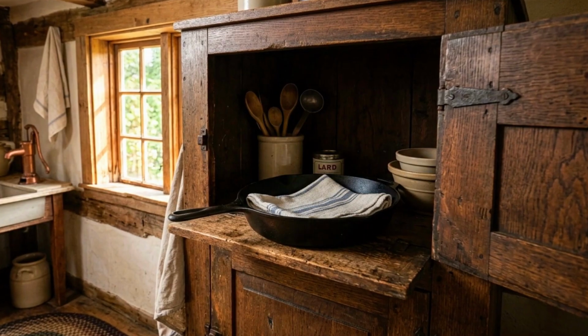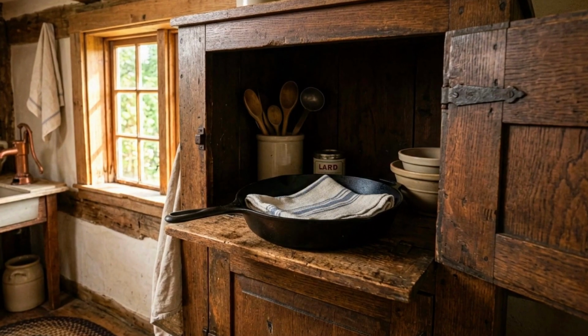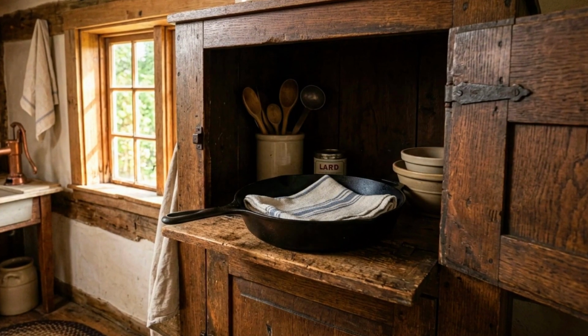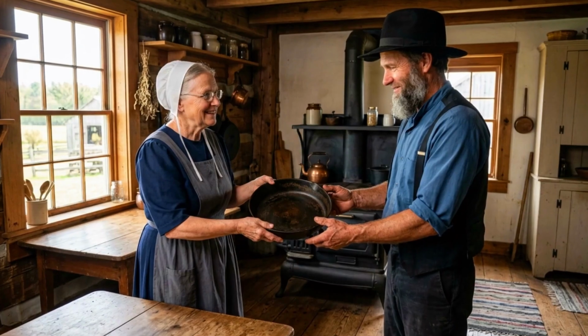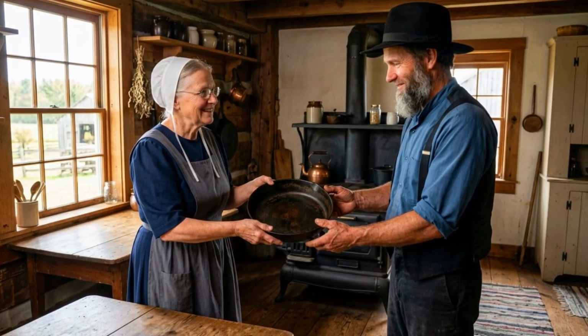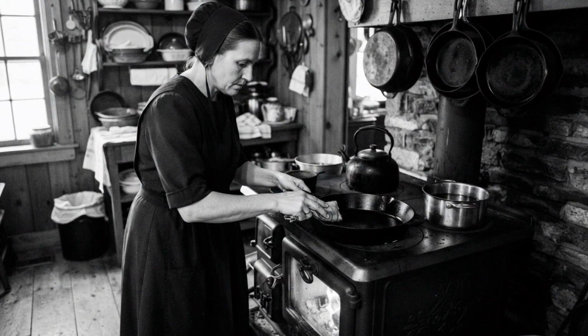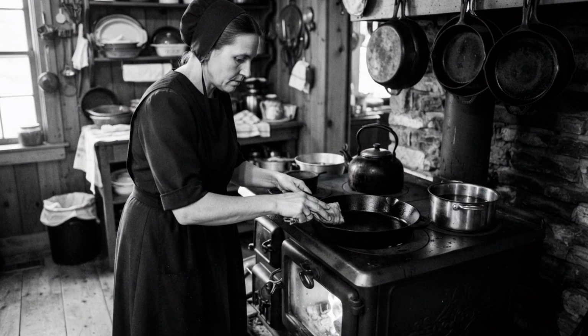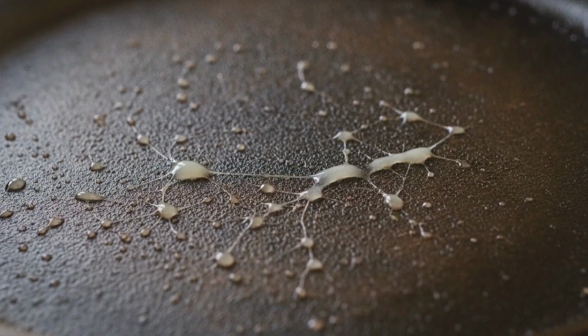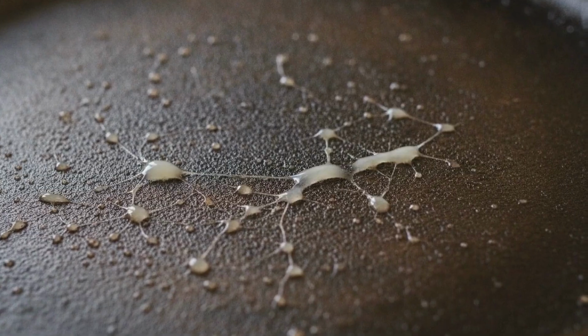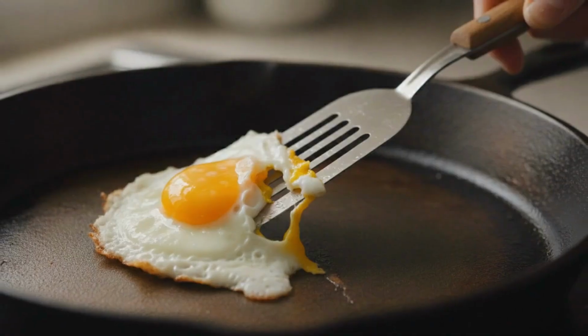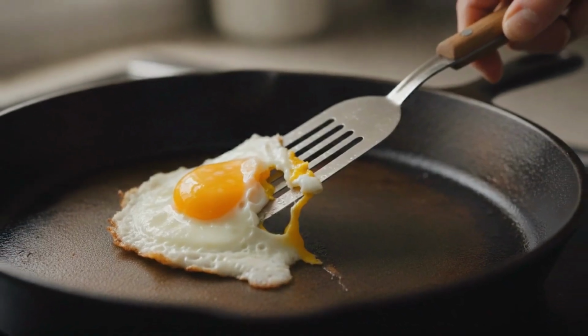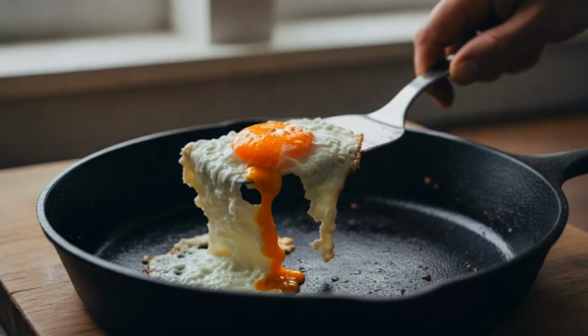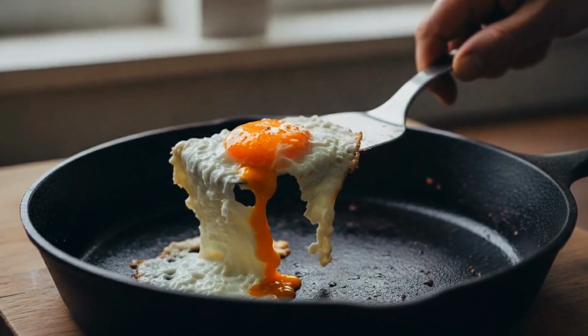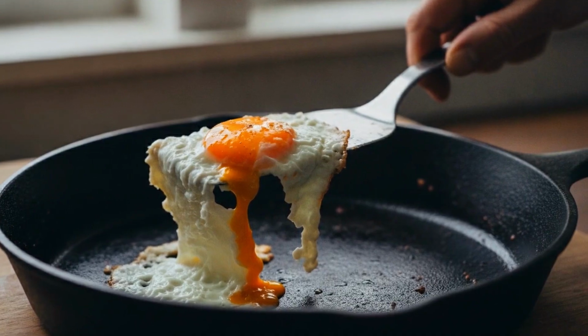The Amish preheat method starts on medium-low heat for 3 to 4 minutes before cooking begins, allowing the pan to heat gradually and evenly through its entire thickness rather than having a screaming hot surface above a cold iron mass. Cast iron holds temperature extremely well, but distributes it slowly, which means a pan placed on high heat develops hot spots at the center while the edges stay cool, producing uneven cooking and uneven thermal stress on the seasoning.